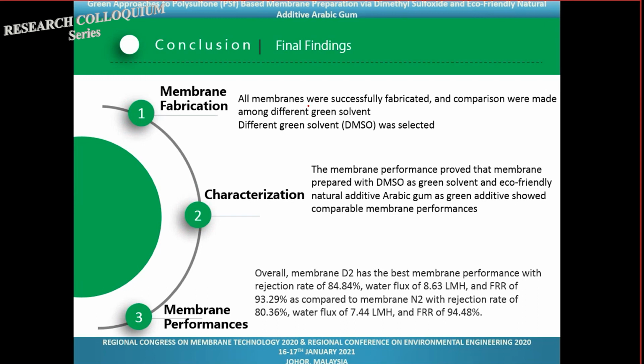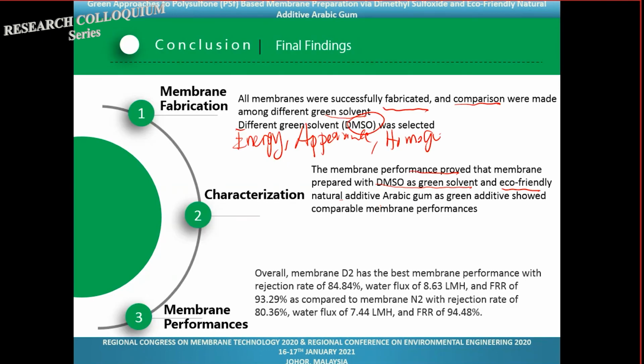Now with all these results, I have come to the final conclusion. First, the membrane was successfully fabricated, and the comparison was made among different solvents, and based on the energy, the appearance, and also the homogeneity, DMSO was selected as a green solvent in this study. Now the membrane performance also proved that the membrane prepared with DMSO as green solvent and also eco-friendly natural additive Arabic gum also shows comparable membrane performance.